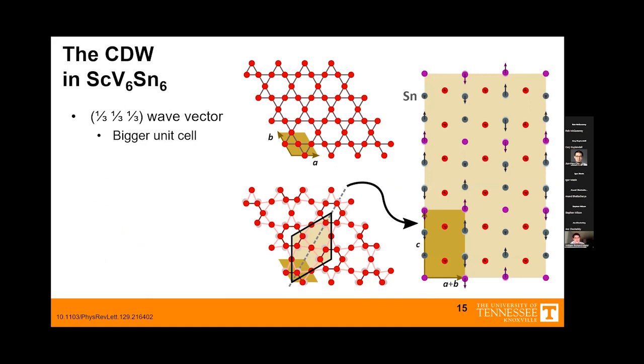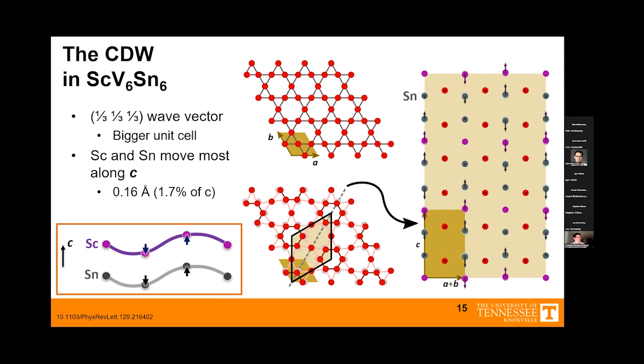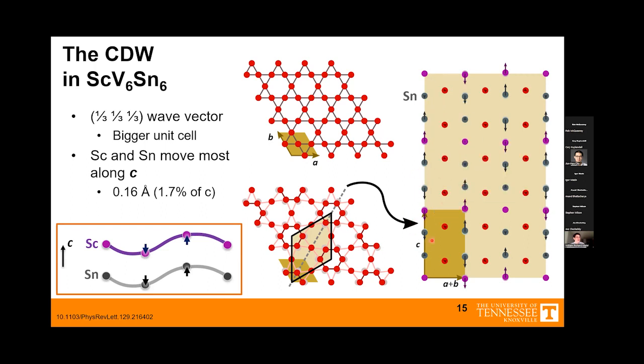And as Stephen pointed out, these scandium and tin atoms are moving the most, and they're mainly moving along the C-axis. The vanadium atoms are kind of spectators here. And they move a big distance. 1.7% of the unit cell is a lot. And we have this periodicity. And I really like what Stephen was pointing out about the trimers. Until I read their paper, I really didn't appreciate that these 3 atoms here are moving together. Their displacements are the same, so that each one of those forms a little rigid unit. And these tin-1 bonds, I'll introduce that a little more in a moment, change either closer or farther together.